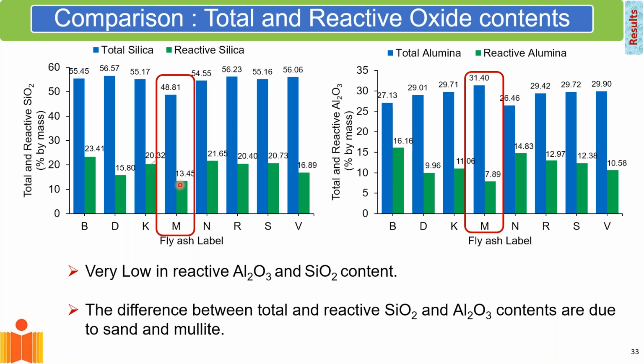Now, if I'm going to simply do a 30% swap of cement with fly ash, I will get very different results. And not surprisingly, when we use this particular fly ash, the strengths were double of what we were getting with this fly ash M. So clearly here, then we need to look at these things a little bit more objectively in order to efficiently use the material so that we don't compromise the performance of cement, rather than going with a prescriptive measure of replacing 30% of clinker or 30% of cement with fly ash.